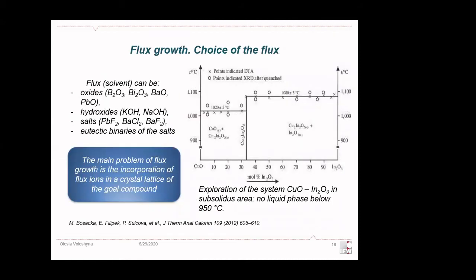So the next approach can be a flux growth of this composition. And usually we use as a flux oxides, hydroxides, salts, or eutectic binaries of salts. Eutectic binaries are an interesting composition of two compounds that have melting points lower than the melting points of the initial salts. But the main problem with such a usual, classic flux, let's call it like this, is that after growth, ions from the flux can incorporate in the lattice of the goal compound. So the next step was to find the so-called self-flux for this composition.